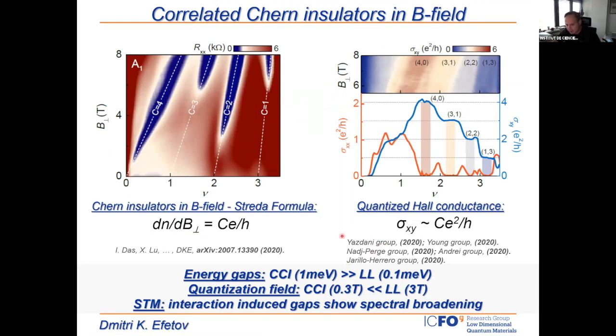And those were, again, prominently Ali Yazdani, Andrea Young, Eva Andrei, Pablo Jarillo-Herrero, who last summer observed very similar results. And really, the experimentally striking feature is that we observe Chern insulators which originate from different filling factors per moiré unit cell itself. So, for example, here, these experimental features correspond to a sequence of Chern insulators of Chern number 4 starting from charge neutrality, Chern number 3 starting from filling factor 1, and so on. So there's always a robust correspondence between Chern number and filling factor.